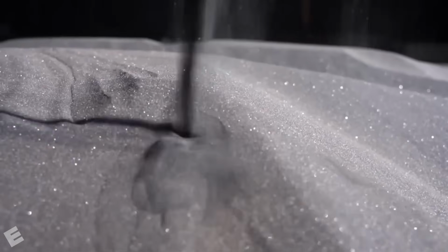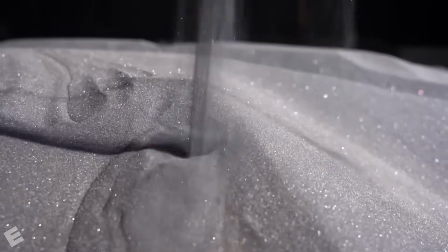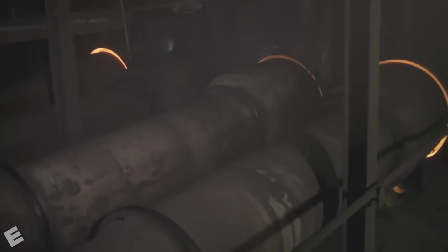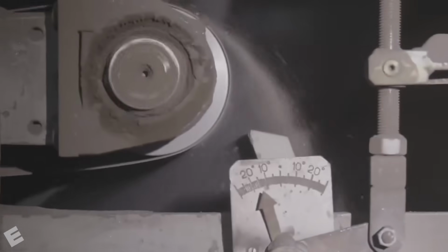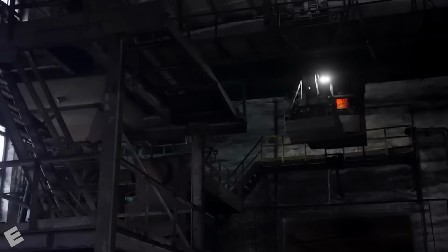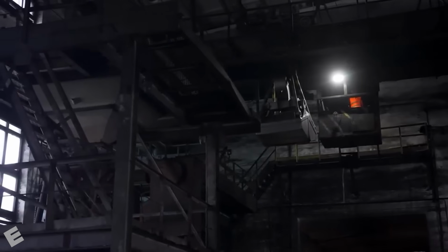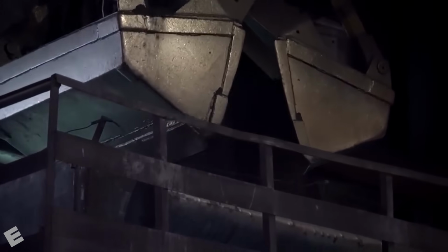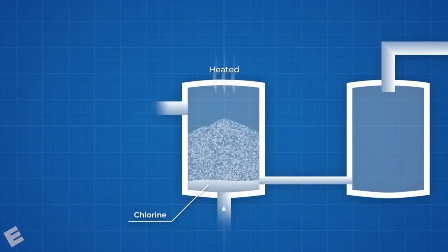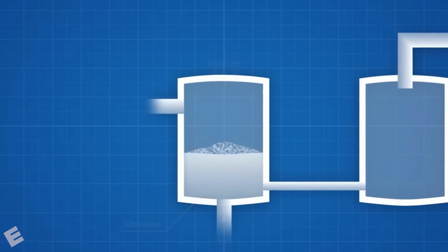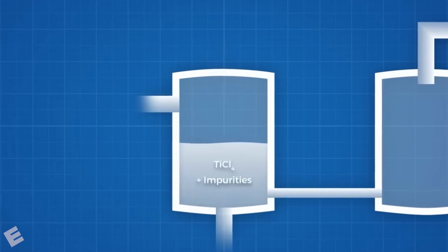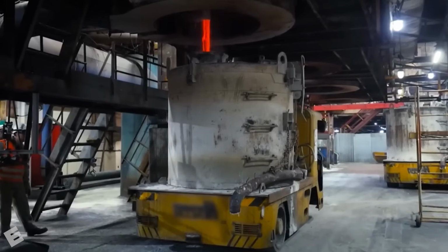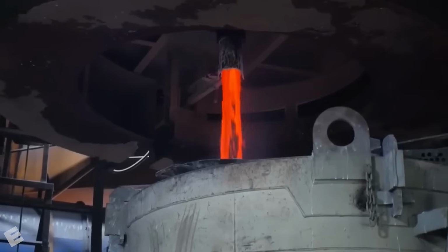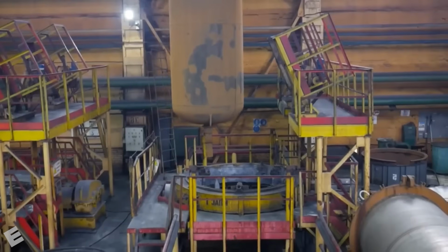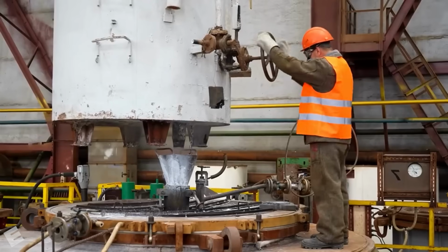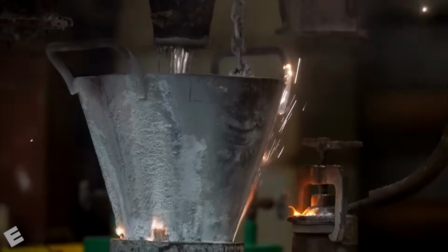To transform this mineral into a metal suitable for aircraft, spacecraft, and other advanced equipment, it must undergo the extremely complicated Kroll process. Industrial facilities produce tens of thousands of tons of titanium using this method every year. The process begins by converting the mineral into a highly reactive chemical compound. The titanium-bearing material is treated with chlorine and carbon under intense heat. This reaction creates titanium tetrachloride, an extremely volatile and transparent liquid. Once formed, the titanium tetrachloride is cooled, condensed, and collected in liquid form.